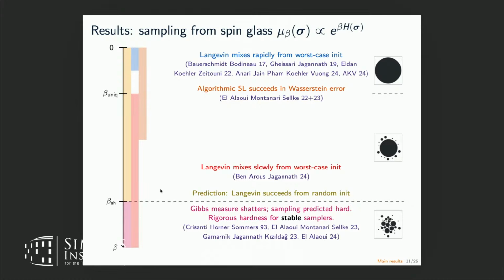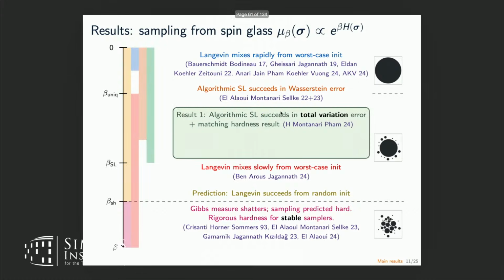Algorithmic stochastic localization will get past this barrier, and works by Ahmed, Andrea, and Mark produced samplers that sampled with vanishing Wasserstein error. Our main result will be a sampler that goes through the algorithmic stochastic localization framework and succeeds with vanishing total variation error. This works up to an explicit inverse temperature beta SL. And we also get a matching hardness result: anywhere above this beta SL, a class of stochastic localization-based methods will not succeed.